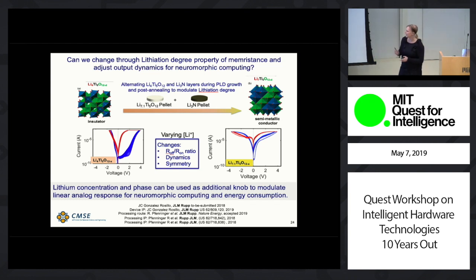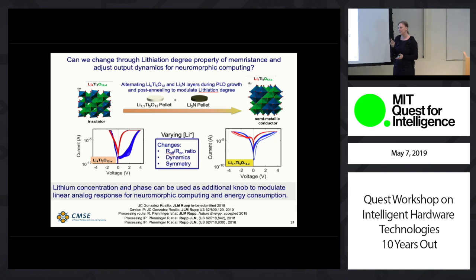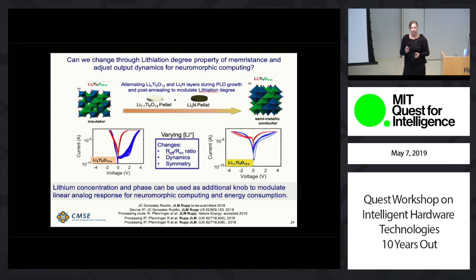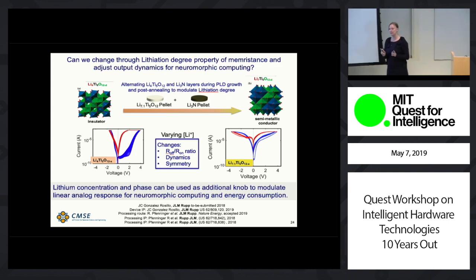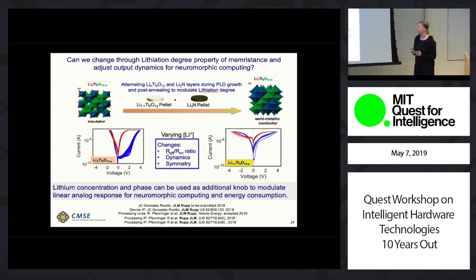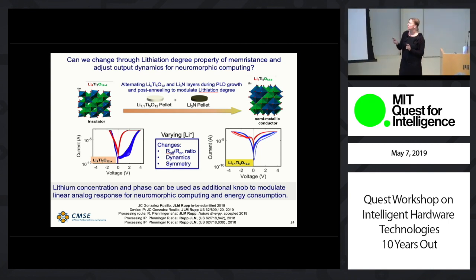And there are three things we can learn from that. The first one is that within one material, depending on the lithium that I apply, I can be either asymmetric or symmetric, and I can change the resistance on-off ratio and the dynamics of the material. That's quite relevant, because what I showed you in the beginning is that you normally don't have much leverage to design materials for fast dynamics while affecting the symmetry and the resistance on-off ratio, because doping can help you a little bit, but not to the extent I show you over here.